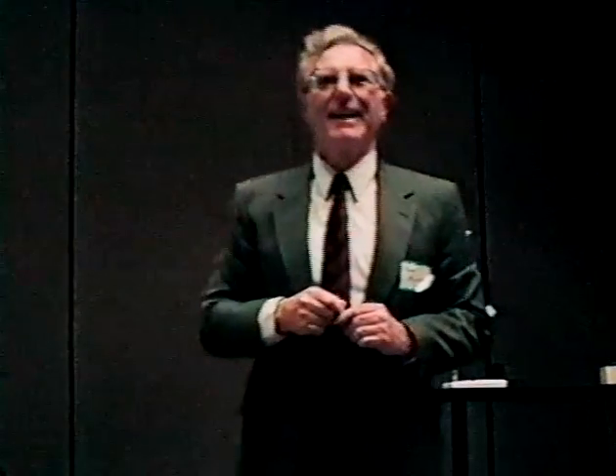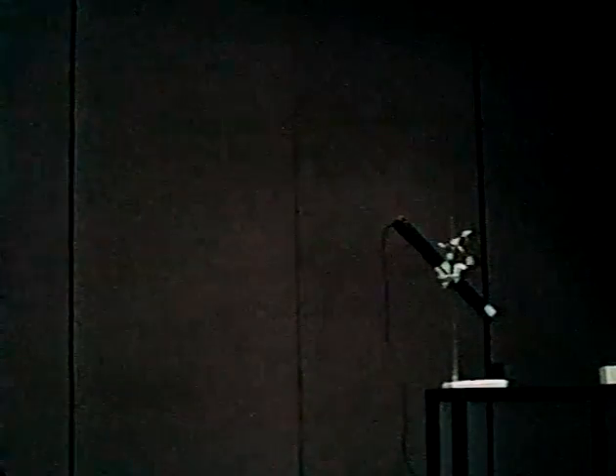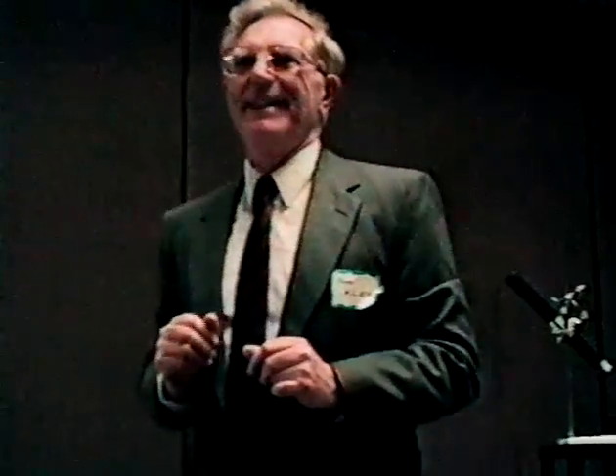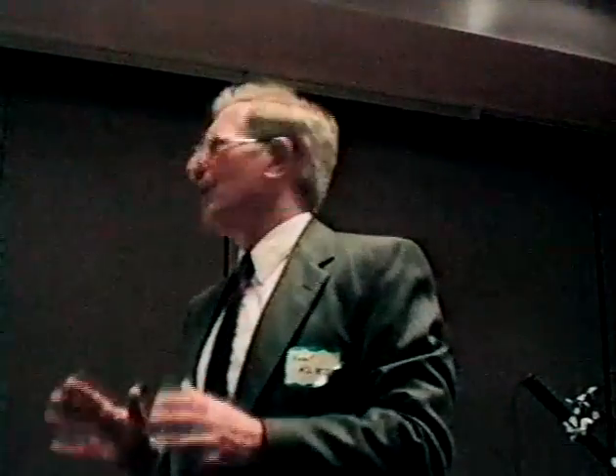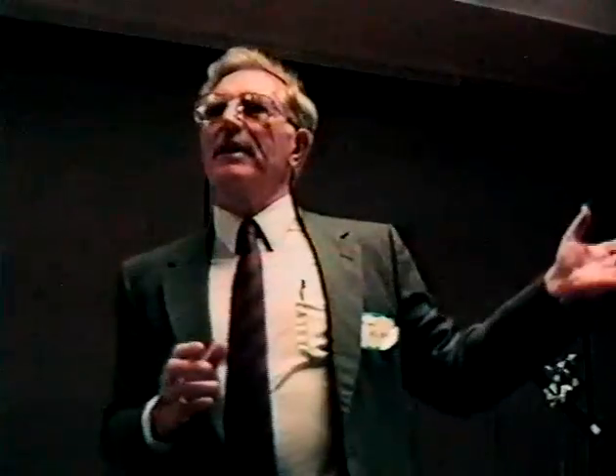You mentioned the case of palladium, that you required the rough surface to get your reaction on. How sensitive is that to the catalyst preparation in the case of palladium? We're still working on this system. The question is whether this particular crystal face is the condition for cracking methane, or can you crack it on other faces? We have not explored them all. I'm just reporting to you a result after a lot of trouble with the 100, which did not crack methane, that this particular plane does it.